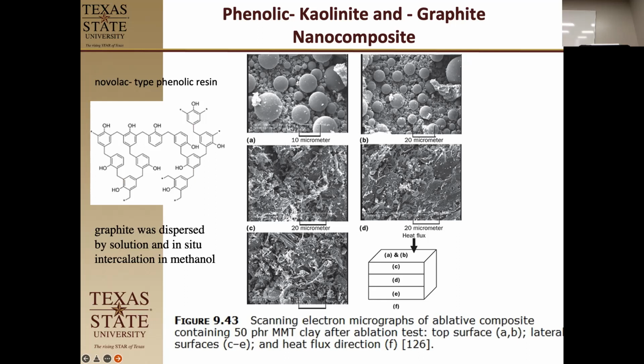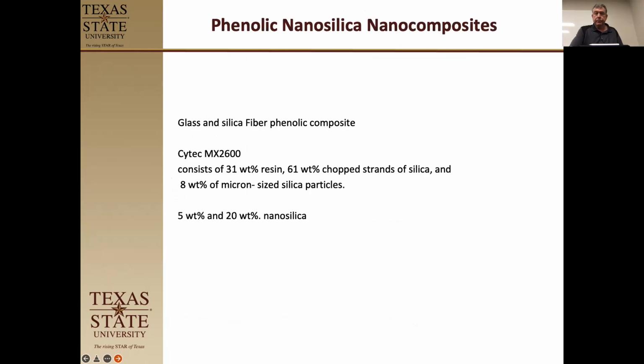So at the surface, you see a lot of damage. But on the side, as we're moving down, this is in the pyrolysis zone, this is out of the pyrolysis zone, this should be in the bulk virgin material zone. So we see a big difference in the system as we go through the thickness of the material. In this one, they used glass and silica fiber phenolic. So the glass is probably the one melting and causing little droplets at the top.